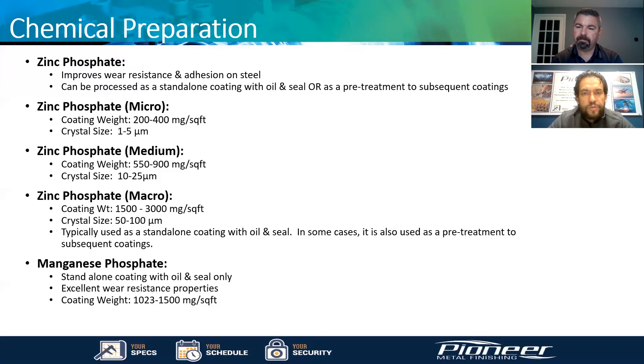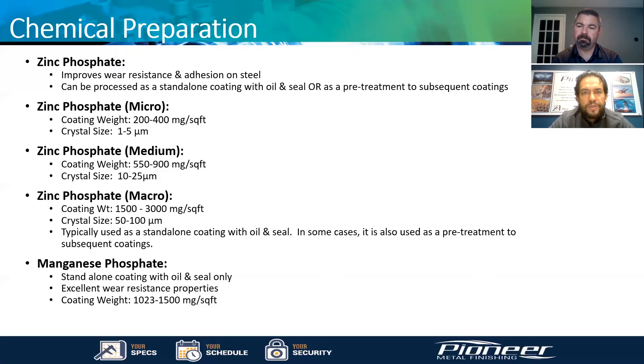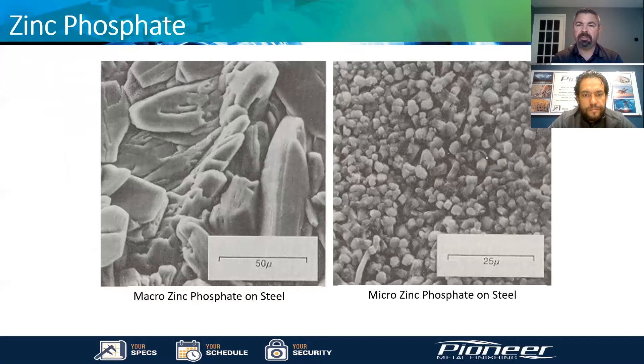That's correct. We have a formulation in our process where, when we launch a project, we discuss with the customer what the final usage for the part will be and whether it's going to be swaged. Swaging typically comes from the outside to the inside — usually for outer cans on a bushing. When we start the project we get aware of this and make sure our program reaches the lower end of the coating weight. We call this a swageable phosphate, which allows customers to swage those parts with confidence without breaking the crystals and risking a debond.